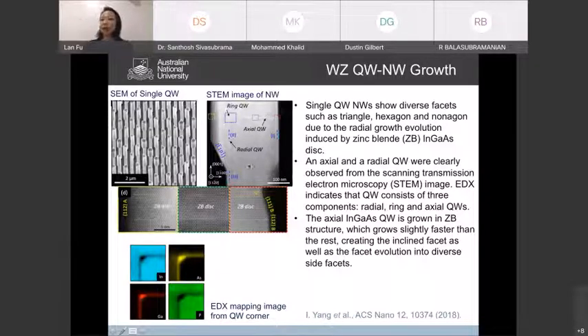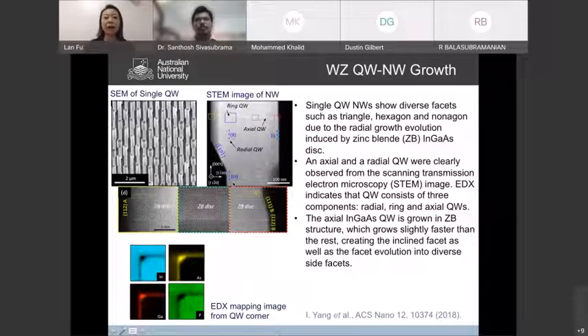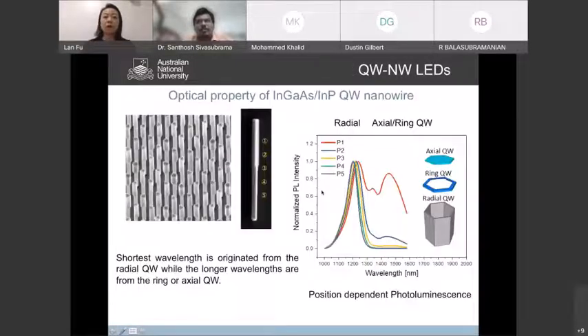If you do a very detailed TEM analysis, we see that with a single indium gallium arsenide quantum well inserted into our nanowire, we have a three-dimensional quantum well structure formed. You have a component in the axial direction and a component in the radial direction. Actually, you have a little corner forming a ring quantum well with a different composition. So it's a very complicated structure, and I'm not going to go into the details of the analysis. This just gives you the basic vision of the quantum well formed in the nanowire structure. Because of this complicated quantum well, position-dependent photoluminescence study shows photoluminescence coming from three different quantum well structures: the axial quantum well, the ring quantum well, and the radial quantum well.